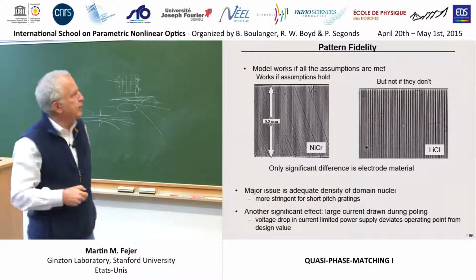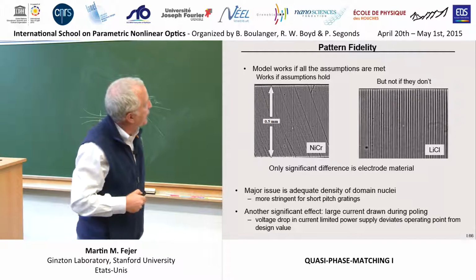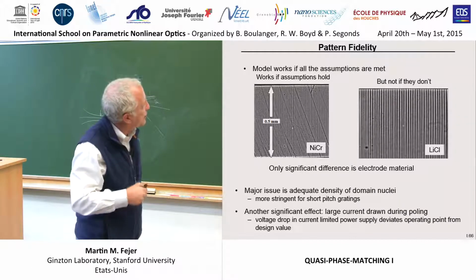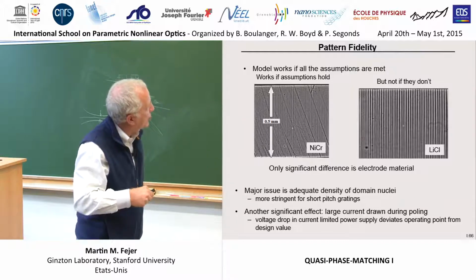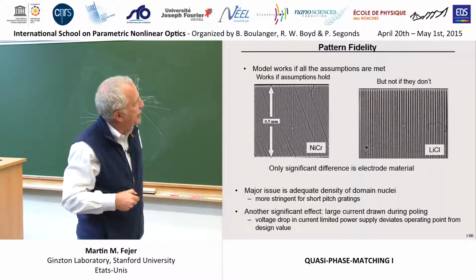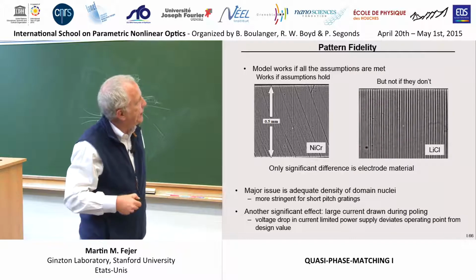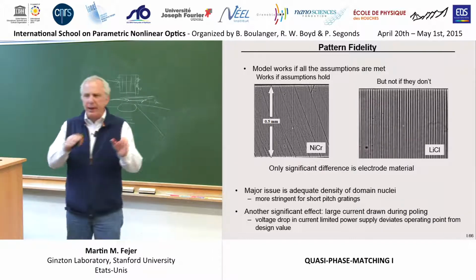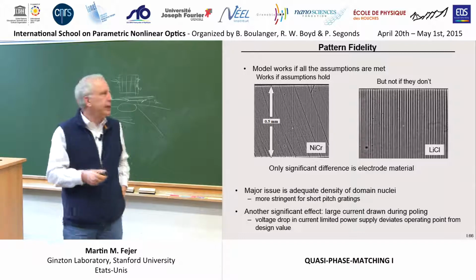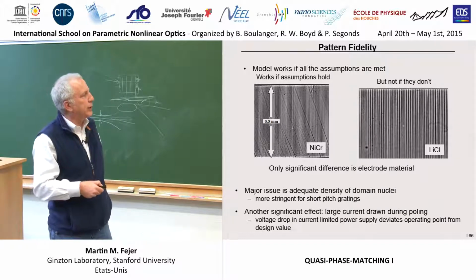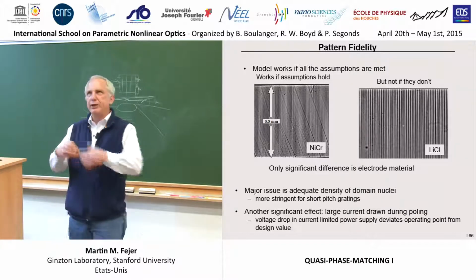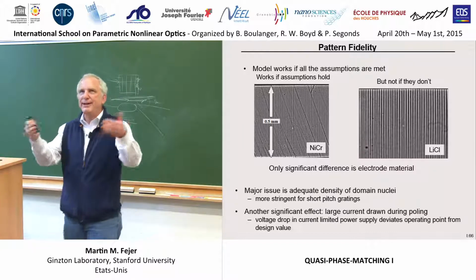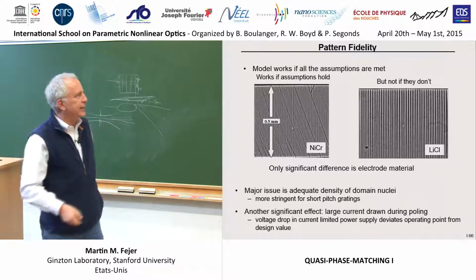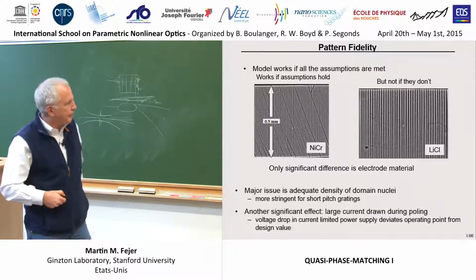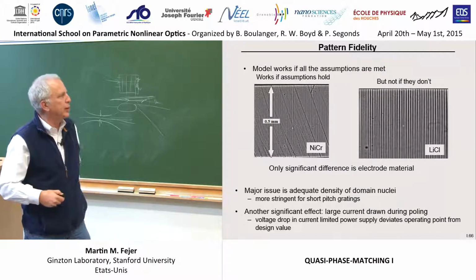If you do things right, this is, I think, a 6 micron period and a 0.5 millimeter thick wafer, and these are just polishing scratches. And you can see the domains are quite regular and uniform. If you do something slightly different, you get a mess. And there are a lot of parameters that matter here. It turns out what you choose for the electrode, whether it's a metal or an electrolyte, you change the nucleation density and things like that. It's a long story. But the takeaway message might be,